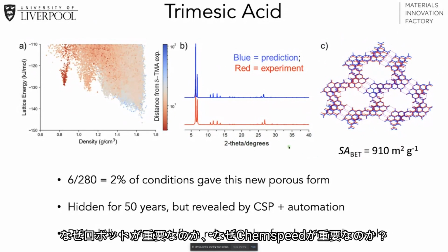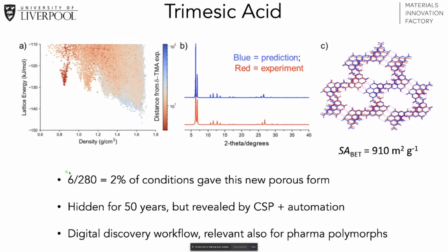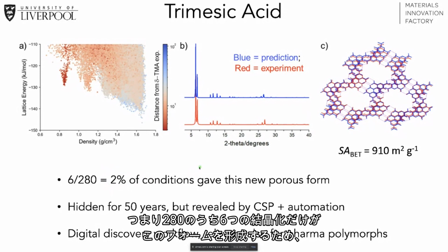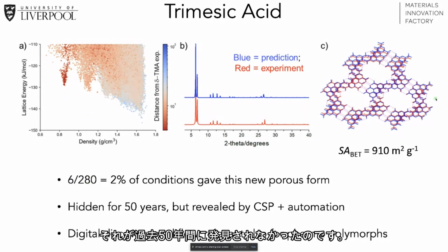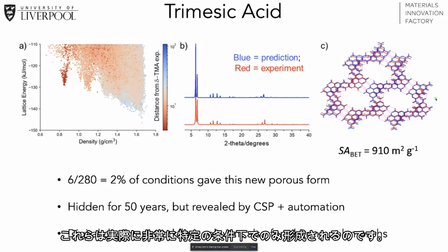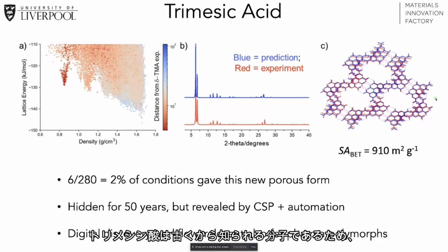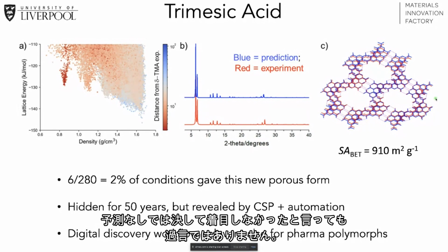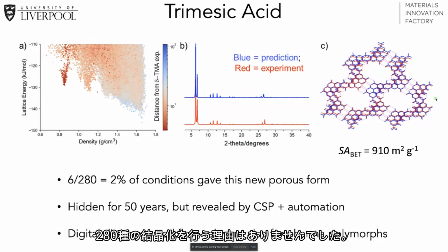And why is the robot important? Why is the Chemspeed important? Well, it actually only forms under 2% of the conditions that we studied. So only 6 crystallizations out of 280 gives this form. And that explains why it wasn't found in the last 50 years. It actually only forms under very specific conditions. And it's fair to say that we never would have looked without the predictions, because trimesic acid is an old molecule. There wouldn't have been any reason to do 280 crystallizations.